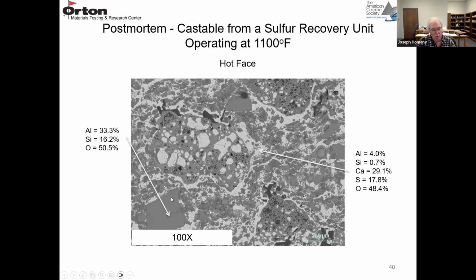So here's an alumina silica aggregate here. And then at the brightest white color phase here, there's some alumina, some silica, but it's mostly lime, sulfur, and oxygen. So that's a combination of elemental sulfur and calcium sulfate.